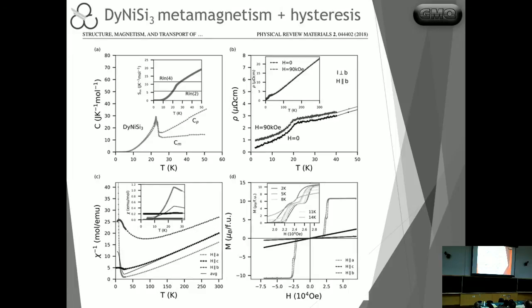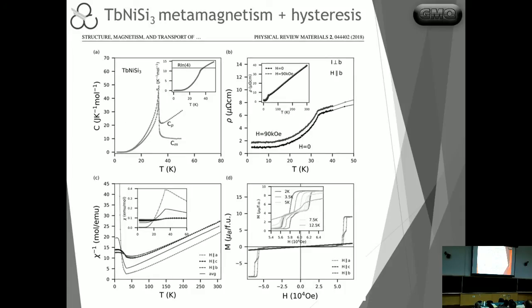So as we move on to terbium, we basically see the same type of features. Once again, as is typical for terbium, in this case, we see an R log 4 entropy coming out like this, which is the typical ground state that comes out in the orderings of terbium compounds. What else do we have here? And different from gadolinium, of course, here in the paramagnetic state, we already have strong anisotropy, which comes out from spin-orbit coupling and the CF parameters like this, right? So we have a favorable alignment all around the A-axis here, again.